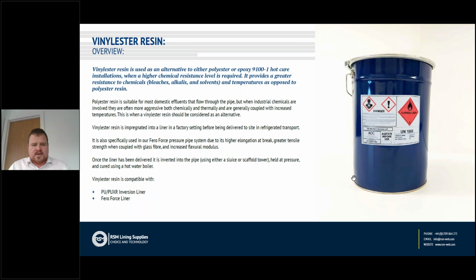Vinyl ester resin, to get the absolute most out of the product, must be factory impregnated and generally hot or steam cured to ensure that we get the very best temperature resistance. Due to the high elongation at break of our vinyl ester, it's also suitable for use with glass reinforced composites. So we get the absolute maximum out of the glass, and increased flexural modulus and tensile strength makes the product suitable for use with not only our Ferroforce pressure pipe system, but also for very large diameter applications and chemical resistance applications.